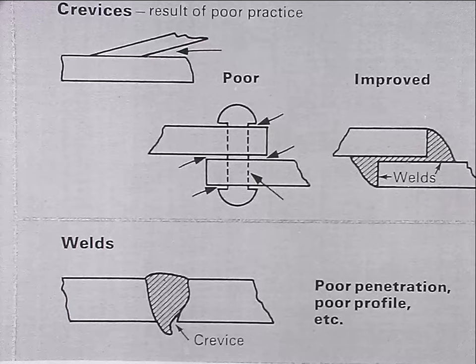And of course in your pipes not only do you have the axial weld, you've also got circumferential welds where you're joining along. So your pipe has got a through wall weld, and it's also where you join one pipe to another, you've then got another weld right round the end to the next pipe. So the penetration of those welds is a very important business, so you don't end up with defects that might give you preferential attack due to oxygen differential.